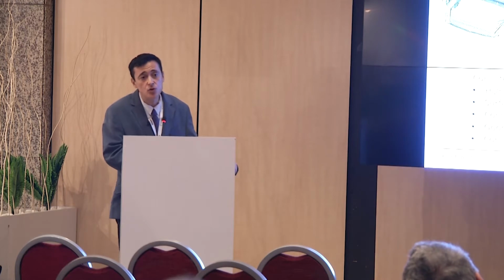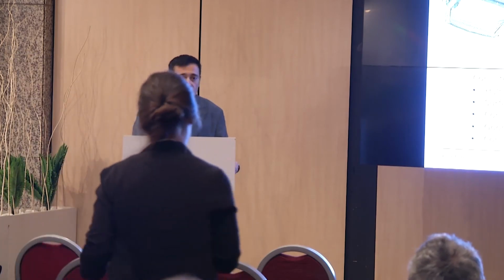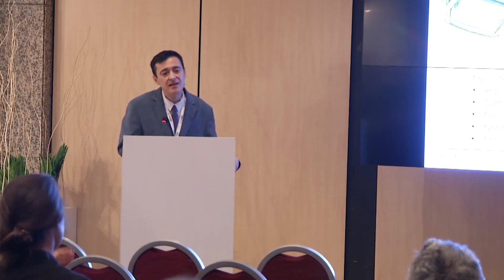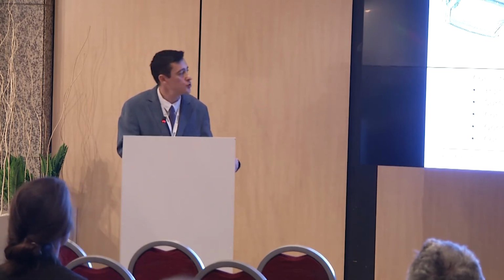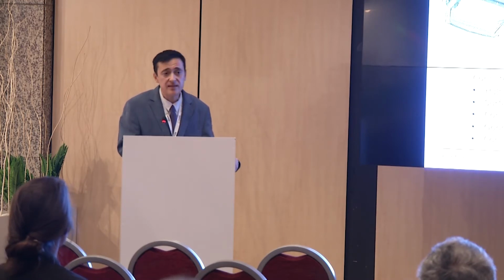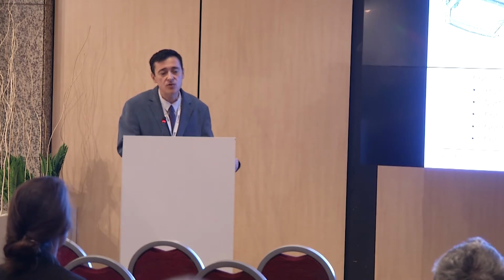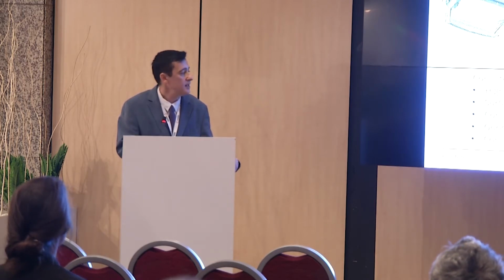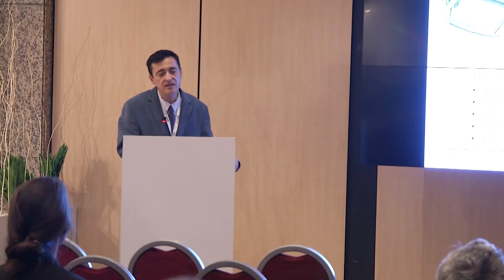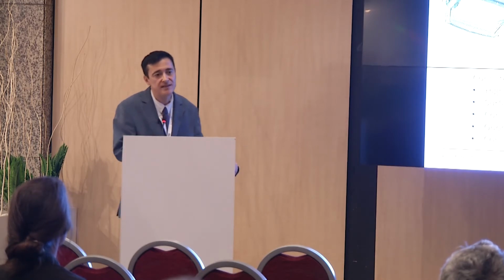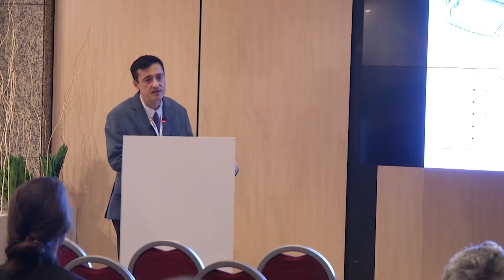It has repeatable and consistent mechanical features, because in the prepreg the fiber amount is changing between 30 and 40. For the RTMs, the fabric amount is approximately 30%. In the prepreg, resin is less and it has more fiber. In the finite element analysis, you see a very good level of correlation. It is not possible to get this correlation level with RTM. And when we look at the mechanical properties, they are much better. And it is also providing you better spare parts.